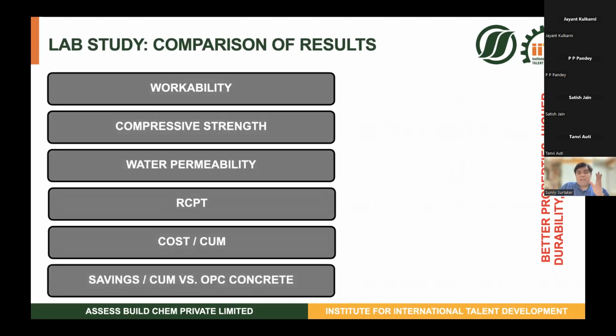Because even in the first step when we started the first building, we saw that in most cases the workability of the concrete mixes on its own was much better than the conventional concrete. Conventional concrete made with crushed sand, or more than that, crusher fines, was simply not very workable, and they had to use very large amounts of water, which in turn affected durability, and even had a lot of problems with admixtures. So we worked on that admixture gradation a little bit and incorporated it into a new mix.